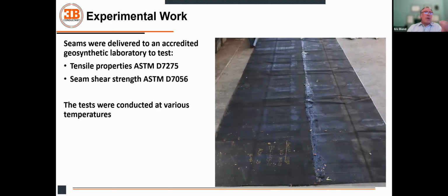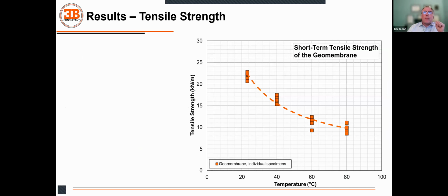So we took this sample and we ran some tests, some tensile tests, D7275, and some seam shear strength tests per ASTM D7056. And we've run these tests at different temperatures, and I will show you after why we did that. What did we get in terms of tensile properties?